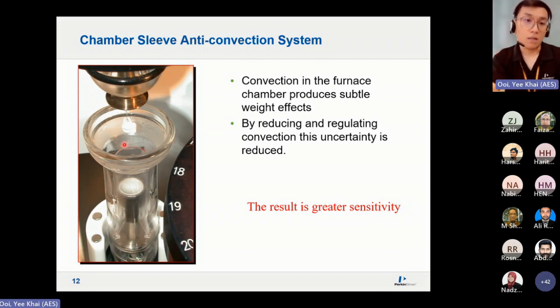So this thing also happens inside the TGA. The lighter gases being heated up, lighter nitrogen going up, and then being replaced by the gas from the surroundings. But this will create what we call a buoyancy effect, causing subtle weight changes, or fluctuation of the weight, which we do not want because it doesn't reflect or come from your sample. So by putting in what we call a chamber sleeve, the quartz chamber sleeve, you can reduce or regulate the convection effects that are happening. This will reduce the uncertainty and result in greater sensitivity towards the weight changes.